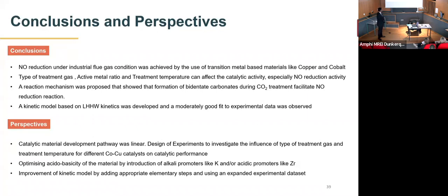The second point that could be explored is optimizing the acidic and basic properties of our material by introducing different promoters, the alkali promoters like potassium or acidic promoters like zirconium. And finally, as we saw before, we can still improve our kinetic model to achieve a higher correlation factor. And moreover, we can also expand our experimental data set in order to help us in determining our model parameters better.